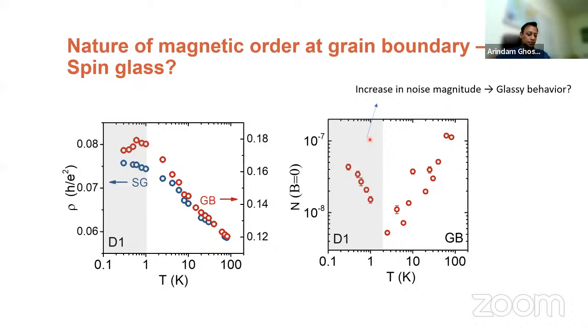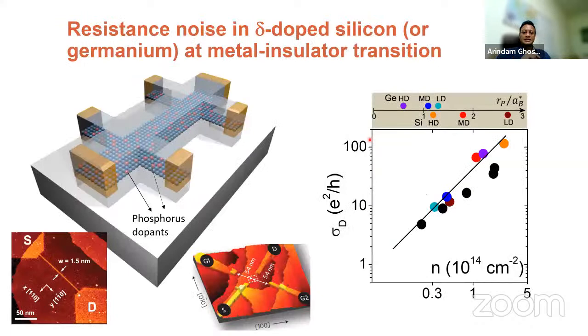Now, we saw a very similar example in delta doped silicon. When I change the density of dopants, as you go down in density, the conductivity starts decreasing. And at a certain point here, there is a metal to insulator transition. So this side is the metallic side, this side is the insulating side. And we wanted to essentially measure, as a function of this doping, how does noise behave in this kind of two-dimensional semiconductors.